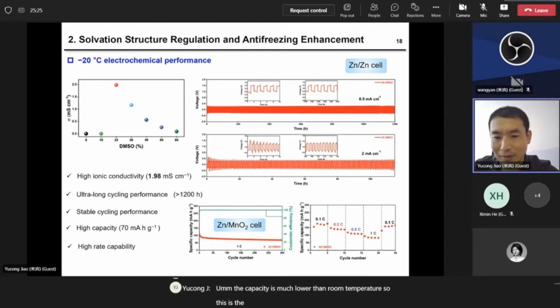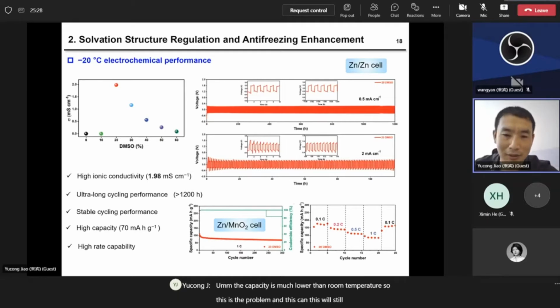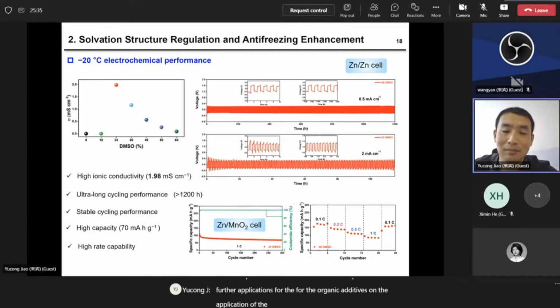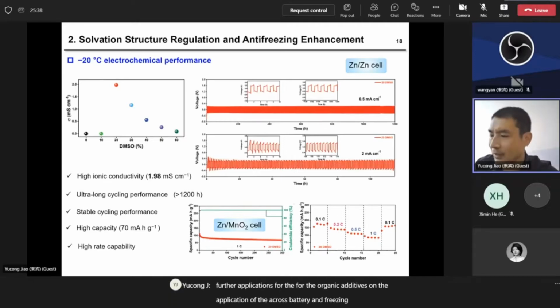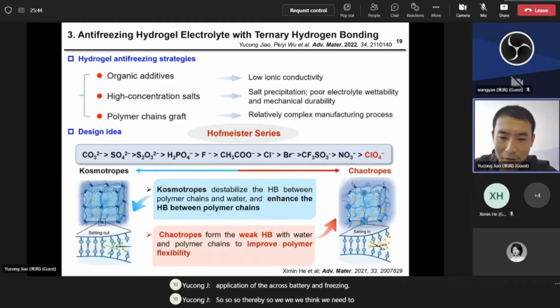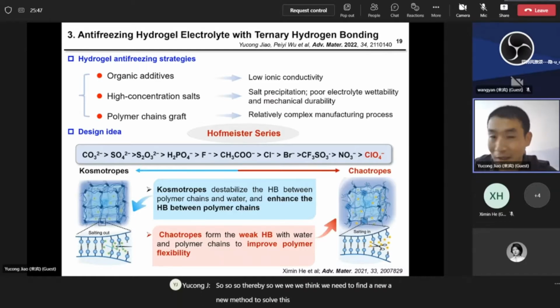So this is the problem, and this will still impede the further applications of the organic additives in aqueous battery anti-freezing. So thereby, we need to find a new method to solve the anti-freezing performance of the battery, and usually we still need to use hydrogels. We can see that for the hydrogels, we can also use organic additives. However, the organic additives, as we mentioned before, have low ionic conductivities.